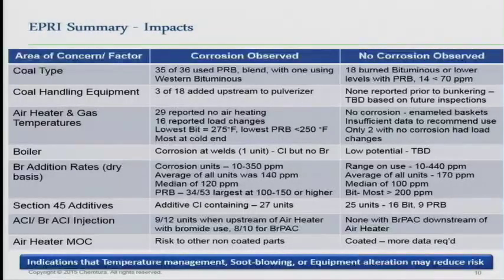On the air heater and the gas temperatures, where they showed corrosion, 29 of those reported no air heating, and 16 reported load changes, so a lot of up and down where you have those temperatures fluctuating quite a bit. Again, just like with the coal type, it basically goes back to if you're dealing with the halogens or the acid gases already, you're more aware and your system is probably better set up than if you're not, and you start seeing that happen more.